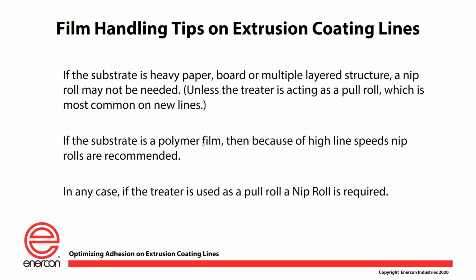And when you combine that with a gauge of film that's very thin, so if you're running 0.5 mil film, let's say even less than 1 mil film, and you're running 700-800 feet a minute on a consistent basis, then we really start having that conversation about the use of the nip roll in a surface treater. And again, if the treater is being used as a pull roll type of setup, then a nip roll is required without respect to any of that.